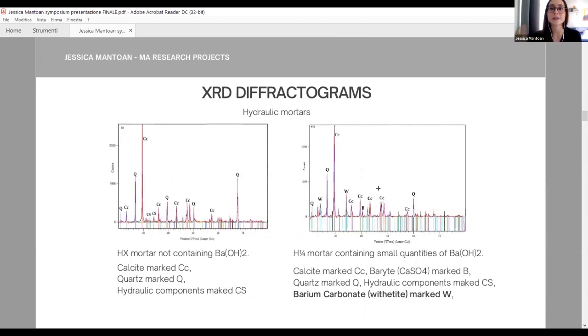Further confirmation of the carbonation of barium hydroxide to barium carbonate was achieved using XRD, where we can see in the diffractogram on the right that together with calcite, hydraulic component, and quartz, we can also see peaks marked with W. That corresponds to witherite, which is the mineral name for barium carbonate.